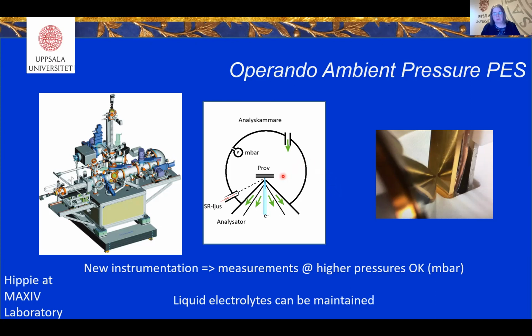And that's good. But if you want to go to the typical electrolytes you have in commercial batteries today, that is a challenge. We are working on new instrumentation and going to millibar pressures. We're working on new sample chambers where you have your sample, you have an analyzer, and you have a little bubble around it where you have your millibar pressure, and then you have a system where you actually increase the vacuum for the electron that you want to probe. So you have several stages of pumping to really reach the outside compartment where you take out the electron. We are working in a specific beamline at MAX IV Laboratory that's built by Uppsala University called HIPPIE.